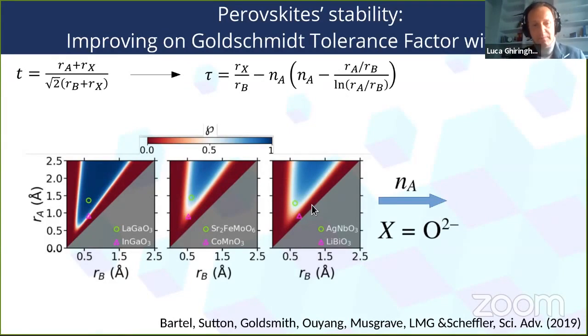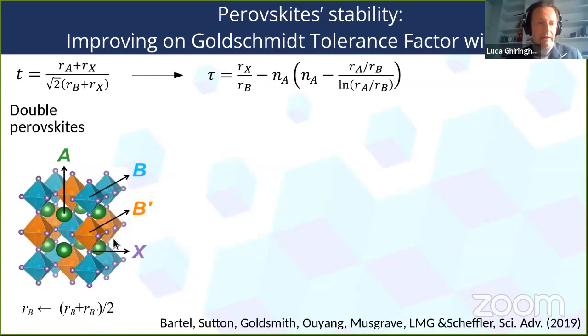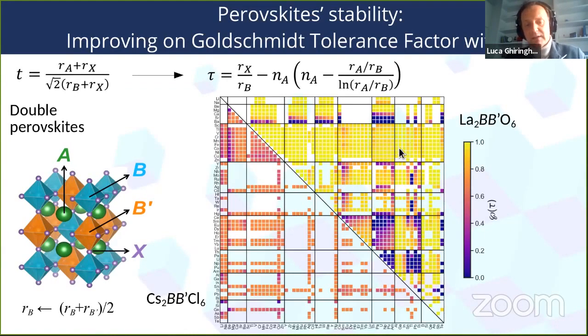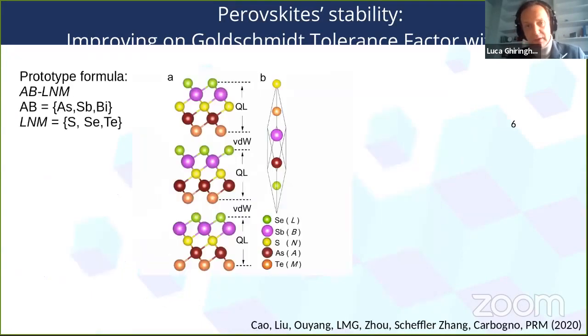Not only that, we can go a step further and say we have double perovskites, in which we have two different cations in the B position, so-called B and B prime. And if we use as radius in this formula the average of the two radii of the two materials, we find a map for double perovskites. Actually, these are two different ones, with cesium or lanthanum. And we confirm what is known experimentally, but we predict thousands of unknown double perovskites that are stable. And the next example actually predicts millions of new materials.